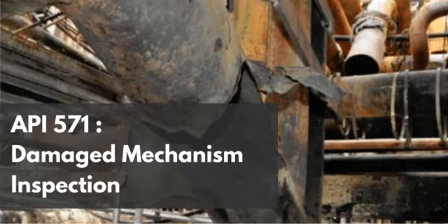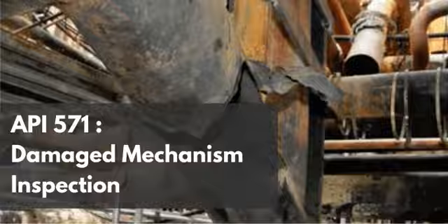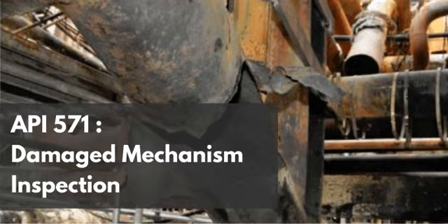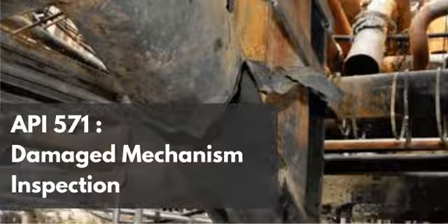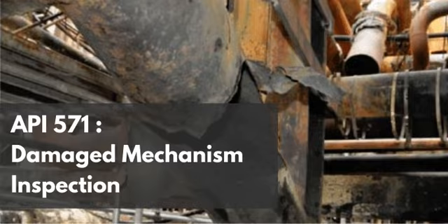Well, we must neutralize one of the 3 required factors for stress corrosion cracking. We cannot change the material, and we cannot remove the amine environment. Therefore, we must eliminate the tensile stress. Exactly. And the API text mandates a highly controlled thermal process for this, post-weld heat treatment, or PWHT. Let's detail the thermodynamics of this mitigation. The text dictates that carbon steel welds must be stress relieved in accordance with 2 specific industry standards, API 945 and NACE SP0472. Yes, those are the governing documents. And the mandatory parameter is a temperature holding range of 1175 degrees Fahrenheit plus or minus 25 degrees. In metric, that is 635 degrees Celsius plus or minus 15 degrees.